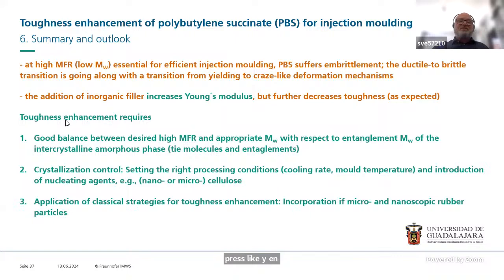So our strategy is to do toughness enhancement, with a good balance between MFR and appropriate molecular weight. That means entanglements must be there in the intercrystalline amorphous phase, tie molecules, entanglements. We must control the crystallization, and we have to apply the classical strategies for toughness enhancement. That is the project we have.